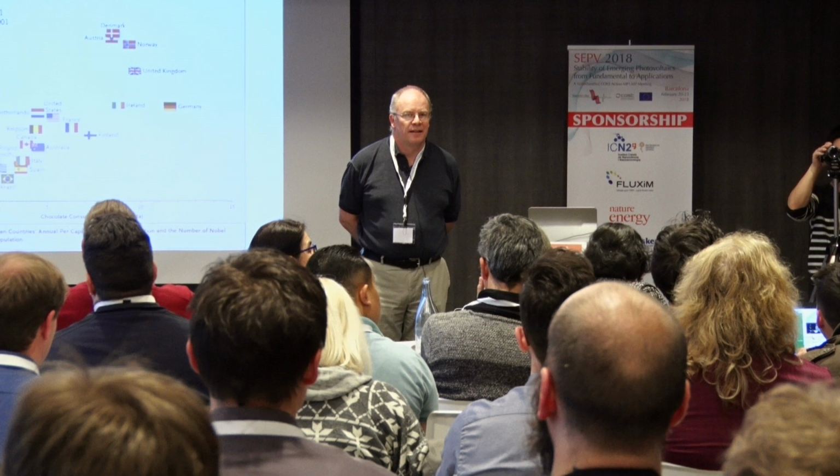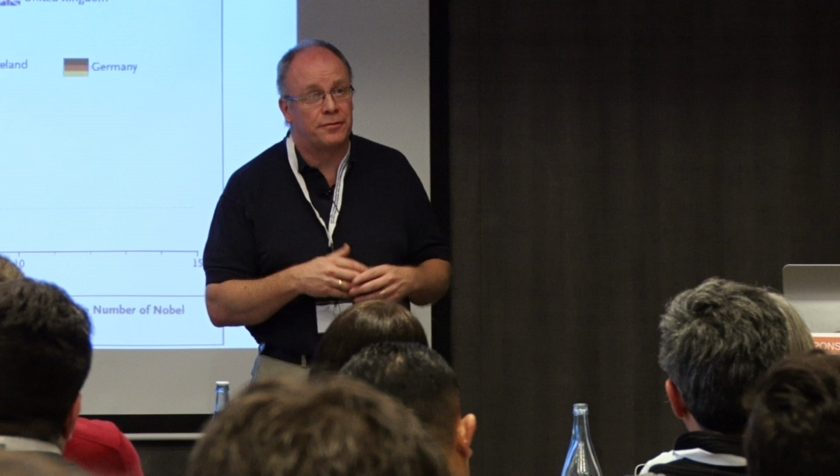Well, the thickness plays a role, but at high temperature you have gold diffusing out, and spiro has voids enough to let it through. That's our picture. We were very surprised with that observation, and people normally are. I know I gave a talk at a PV conference, and one said, well, we know this from organic electronics. It's nothing special, actually, he said. So it has probably been well known, but for us it was surprising.